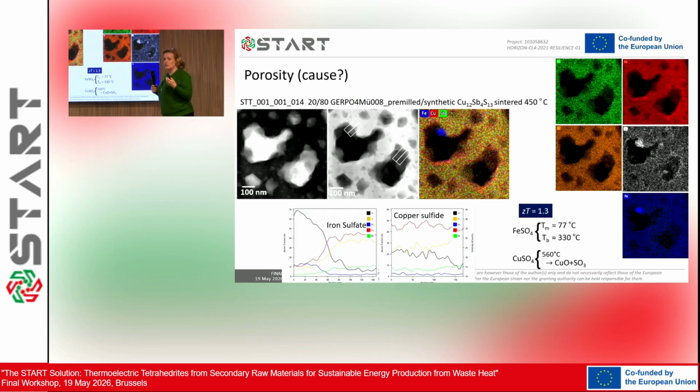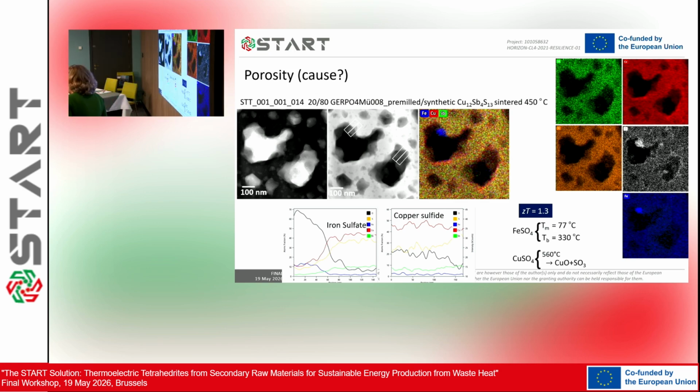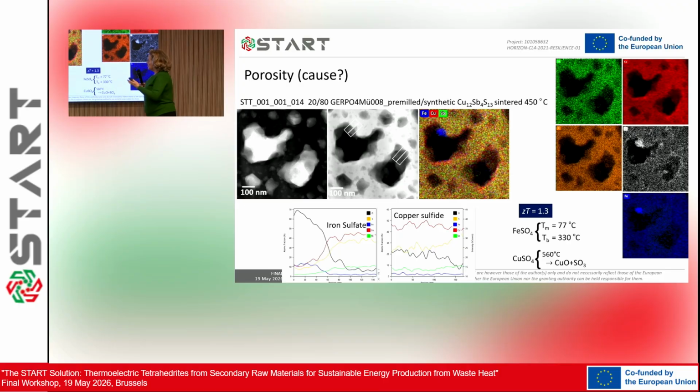But you see, if you look at the numbers, the ZT and the temperature of sintering, and you don't look at anything else, there's very little you can conclude, because you need to characterize the pores, and you need to characterize what's inside the pores. It means that you had oxygen and the oxygen is no longer in the structure, so it's much more complex.